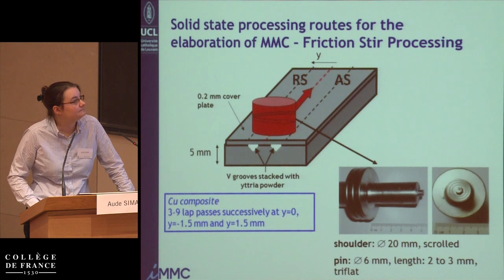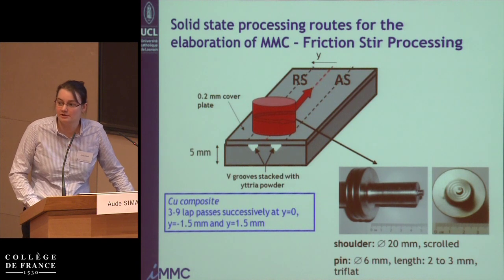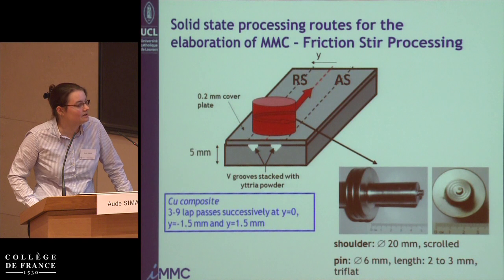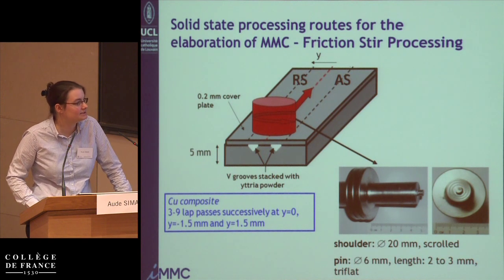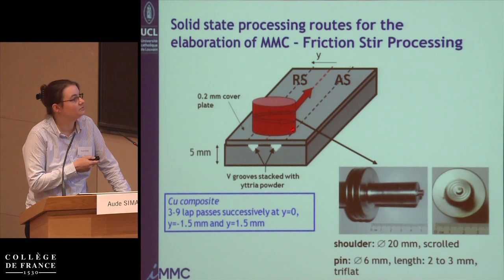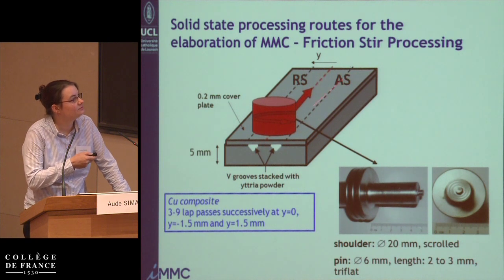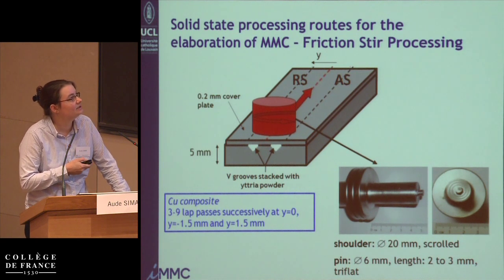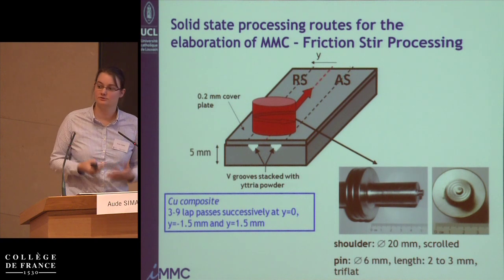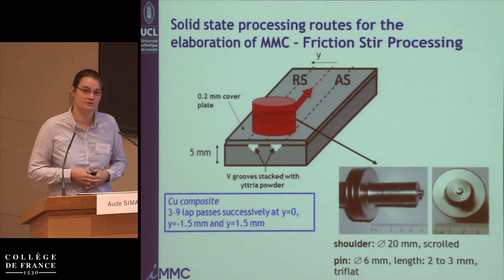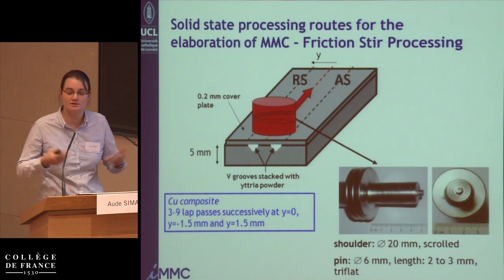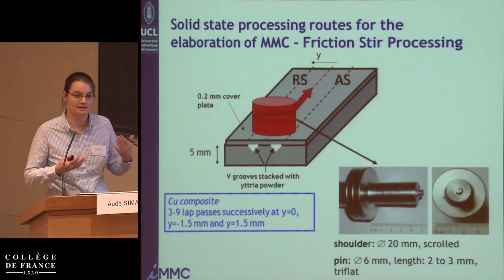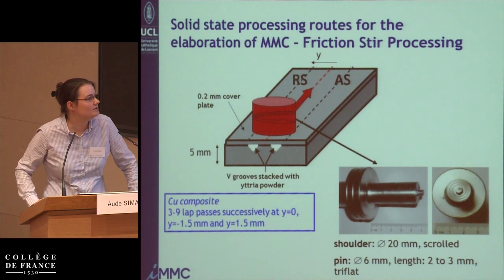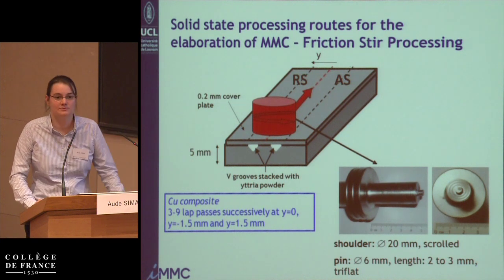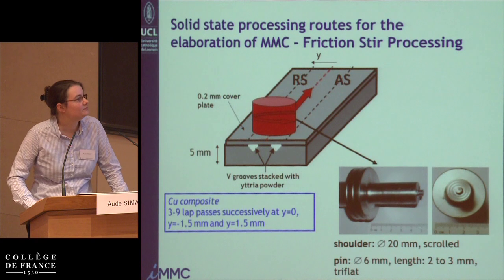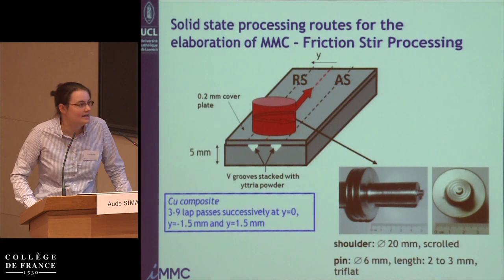So what have we done practically to produce this metal matrix composite, this copper matrix composite, where we have put some yttria powder inside grooves that go all through the material for avoiding that during the process the oxide particles fly away, because it's very light and there is a lot of wind when you're processing. We put a very small cover of copper on top of all that, and then we take our tool, and